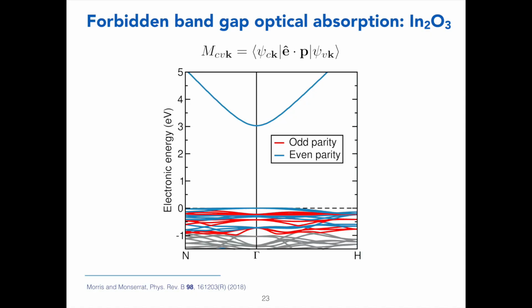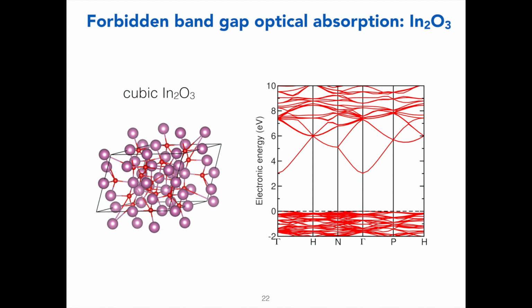However, if I look at this in some more detail, here I'm just zooming into this region of the minimum band gap. What I'm doing now is coloring the bands according to the parity eigenvalue at the gamma point. What does that mean? This indium oxide structure has inversion symmetry, so parity is an operation that commutes with the Hamiltonian, and at a place like the gamma point, that means I can classify all the eigenstates of my system according to the parity eigenvalue. And if I do that, I learn that blue is even and red is odd. So the conduction band is blue, and the valence band is also blue. So that means they both have the same parity.